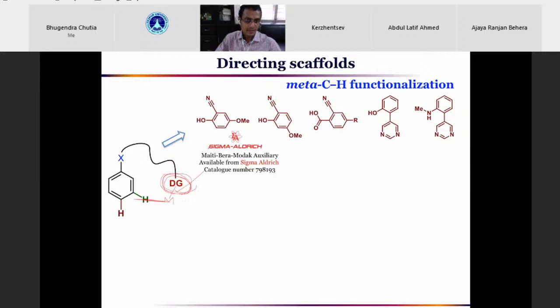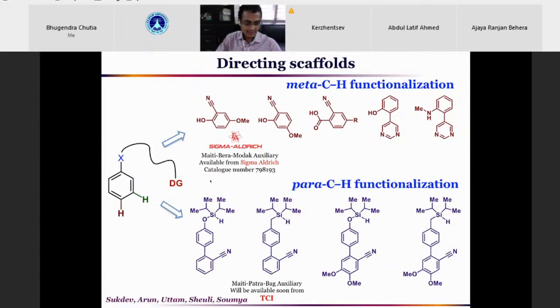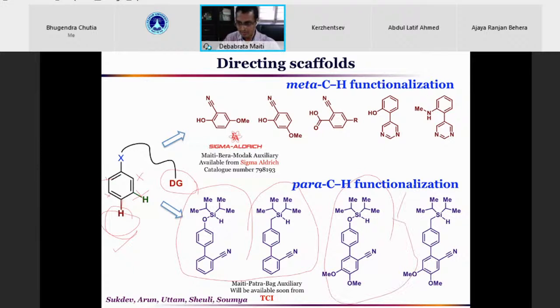For this DG, you can use this one, which is now commercially available from Aldrich. If you want the best ligand, as I was telling you, this is the best DG or ligand. So this is the best one so far for the meta-CH bond activation. If you want the para-CH activation or para-CH bond functionalization and any reaction, let's say at the para position you want to do selectively without touching the ortho as well as meta-CH bond, you don't want any reaction here or here or here or here. You just want the para-CH bond to be activated, then these are the first generation template. This is the second generation template that we are looking at.